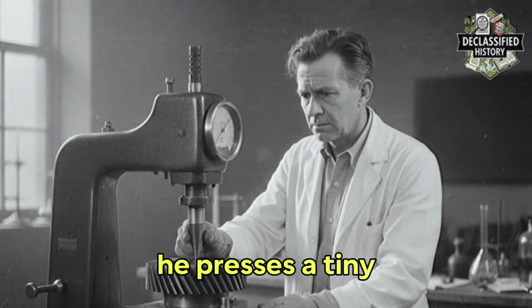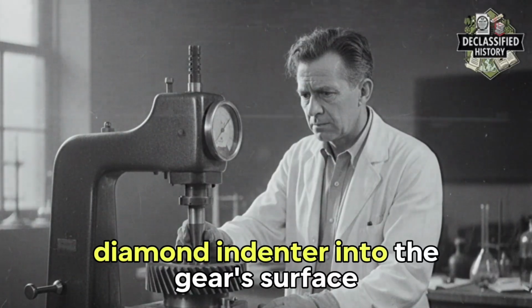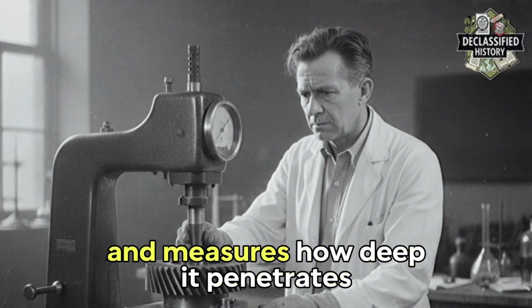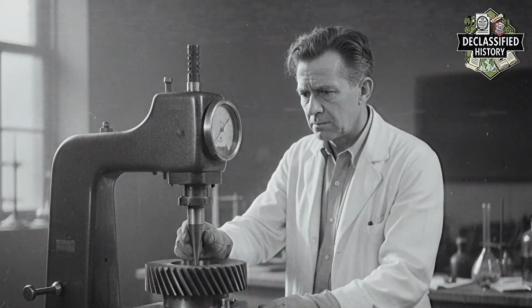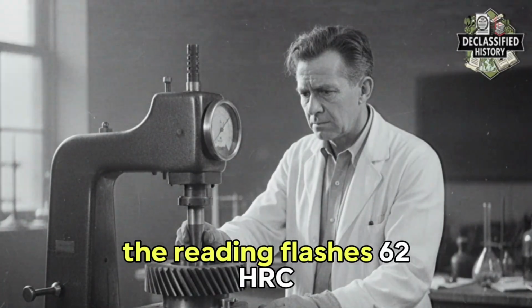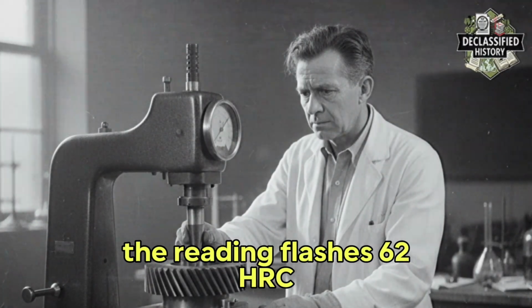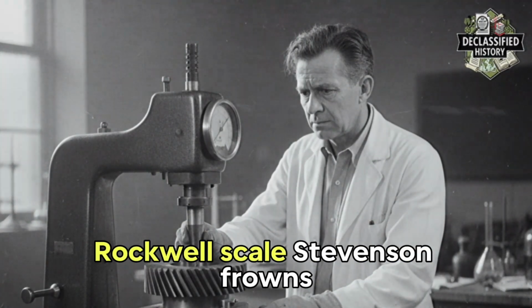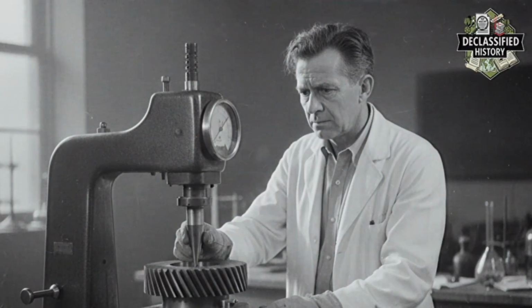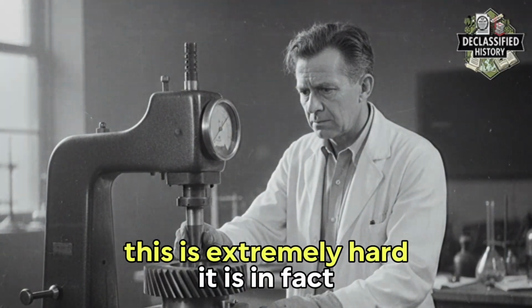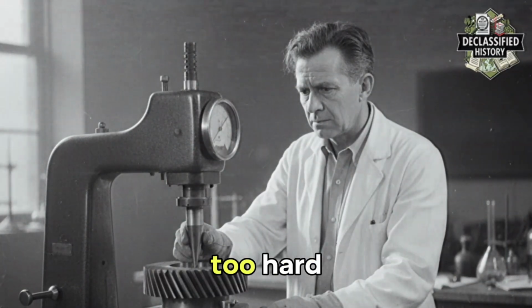He presses a tiny diamond indenter into the gear's surface and measures how deep it penetrates. The reading flashes, 62 HRC, Rockwell scale. Stevenson frowns. This is extremely hard. It is in fact too hard.